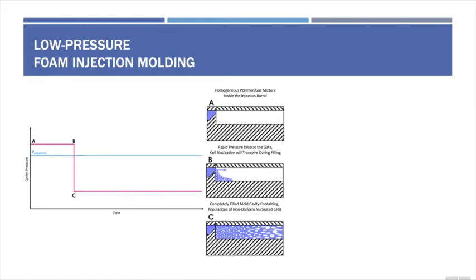Foam injection molding is a method of producing lightweight polymeric foam materials. It is similar to conventional injection molding, but involves the implementation of supercritical gas to produce parts containing voids. There are generally two classifications of foam injection molding: low pressure foam injection molding and high pressure foam injection molding. In low pressure foam injection molding, the molten polymer is saturated with gas, and the saturated polymer gas mixture is directly shot into the mold cavity.